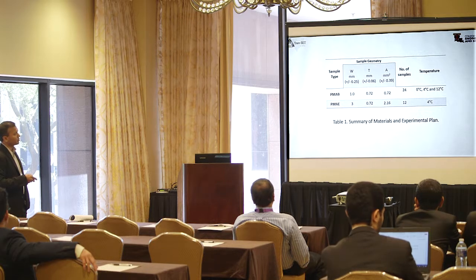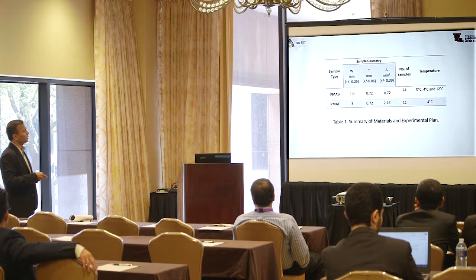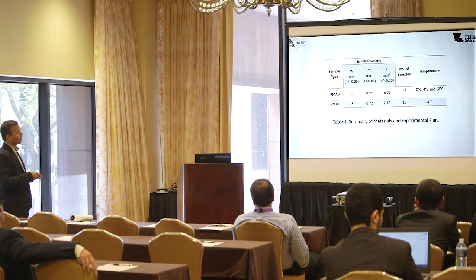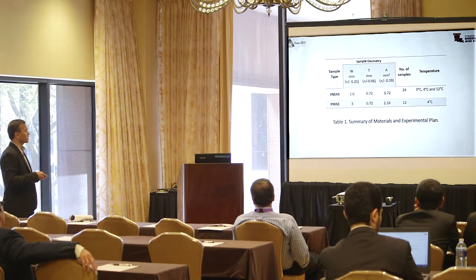The temperature, for force ductility, we usually used 4 degrees Celsius, so it's 4 degrees Celsius here. And then here you can see 12 samples, so at each temperature we used 3 samples for 0%, 3 samples for 2.5, 3 samples for 4, and 3 samples for 5.5% polymer. That's how we got 3 times 4, these 12 samples.